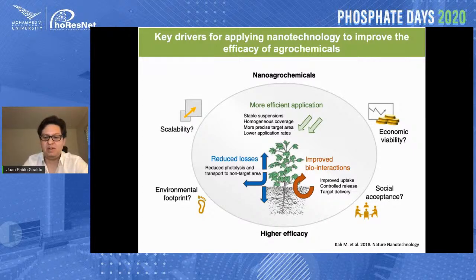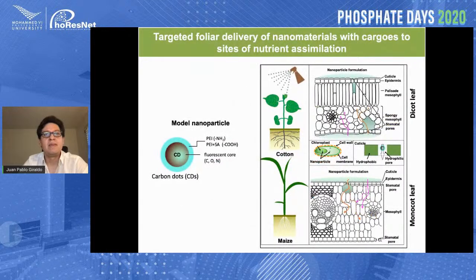we need to be mindful, as Leanne pointed out from the beginning, in designing materials that not only can target nutrients, but also comply with all these other requests in order to have an impact in the field and of agriculture. So with that in mind, my lab has been looking into ways to use more benign, sustainable nanoparticles like carbon dots that are made of organic chemicals found in plants. They're made from basically urea and citric acid. They have a carbon, oxygen, nitrogen core that can be biodegradable. And these particles are fluorescent, so they allow us to track them inside of the plants.